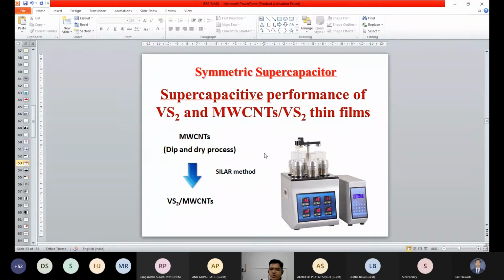So why is vanadium chosen? Because it has a higher oxidation state, so it can show better performance in terms of specific capacitance, and it is embedded on the carbon nanotube, which I have just shown you, the dip and dry coating. And for vanadium sulfide, we have chosen the SILAR method. So what does SILAR mean? Successive ionic layer adsorption and reaction method.